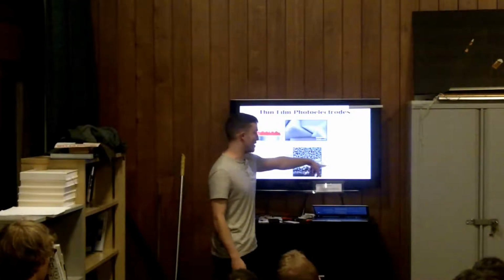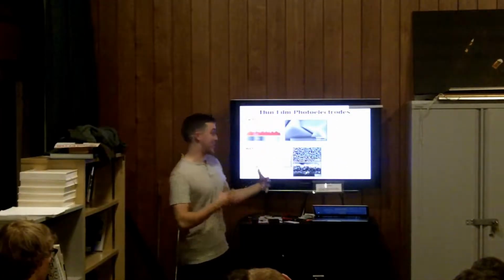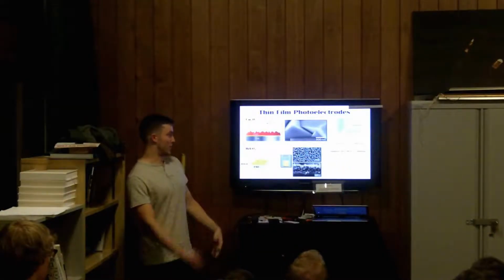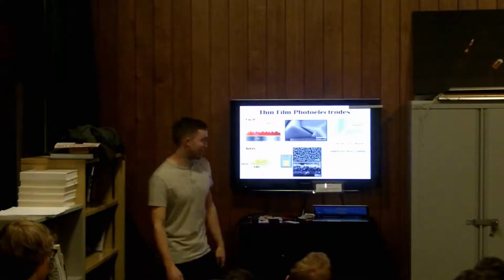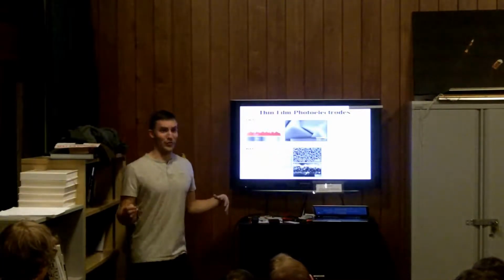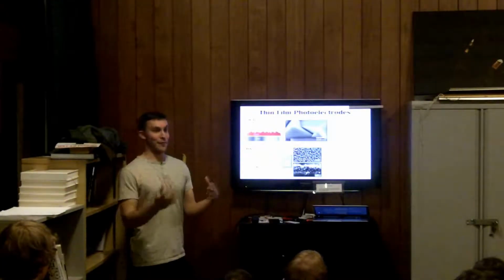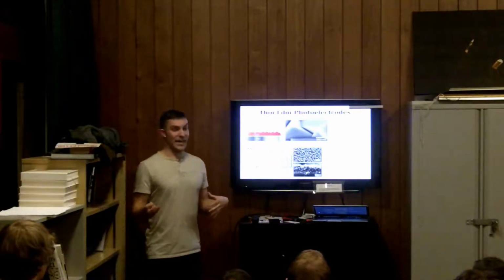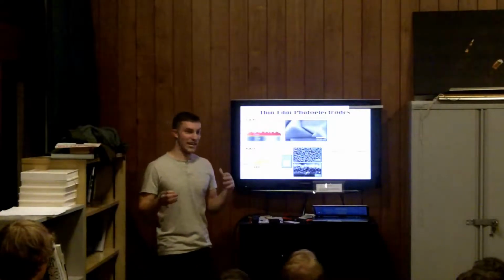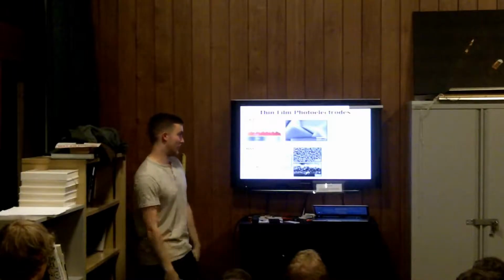And there's good agreement between the amount of oxygen they expected to produce based on the current, and also the white circles, which are the amount of oxygen they actually measured in the system. However, the efficiency, while actually quite good for the field, is still really, really modest: 1.72% efficiency. But this is actual efficiency. This is the amount of energy that we've stored from the sun. We've stored 1.72% of the amount of energy that impinged upon the photoelectric material. So it's great that we can actually quantify that.